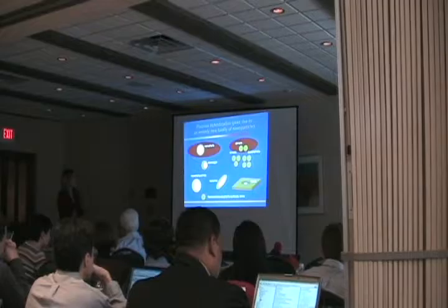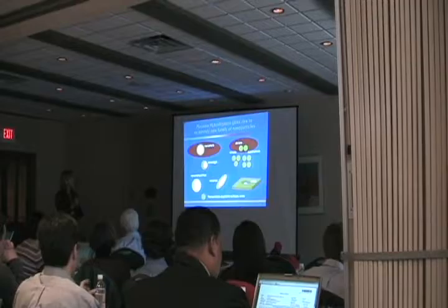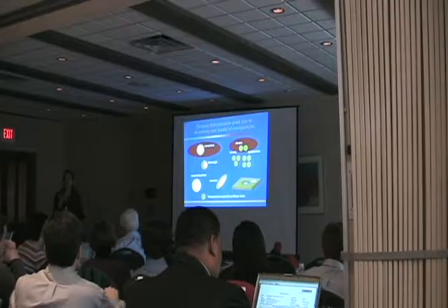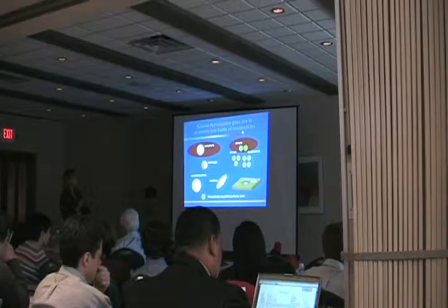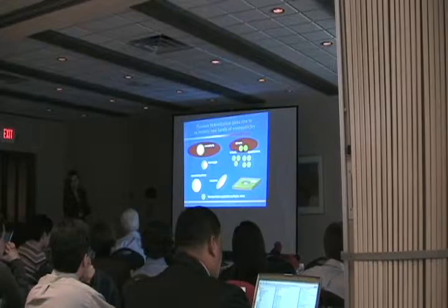So actually, in the context of SERS measurements, we recently did a really quantitative study where we just compared nanoshells to dimers head on in single particle SERS, combining that also with some calculations to see if we could be as quantifiable and rigorous as possible and compare the relative magnitudes of, say, a nanoshell covered with a Raman active molecule versus a dimer covered with a Raman active molecule, the dimer which will, of course, give rise to a much larger field in its junction on resonance over a much smaller surface area.